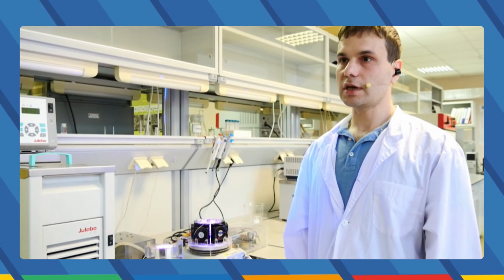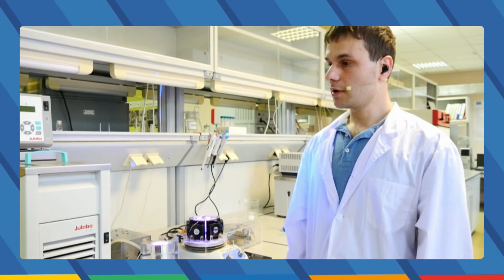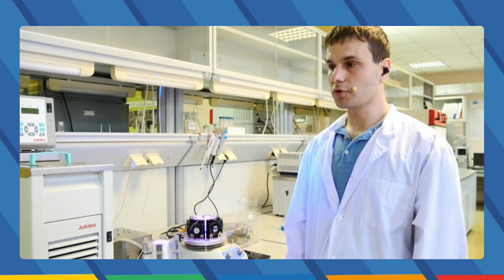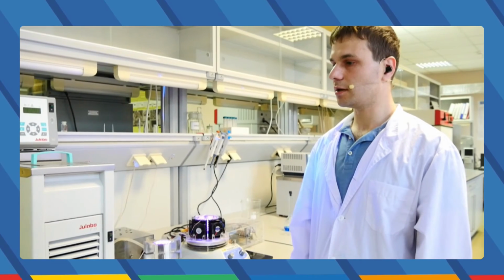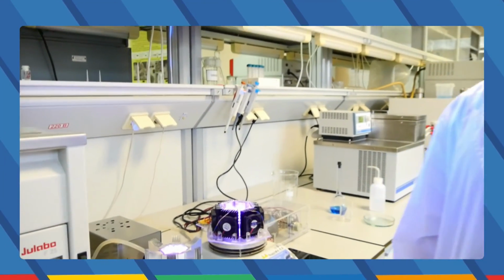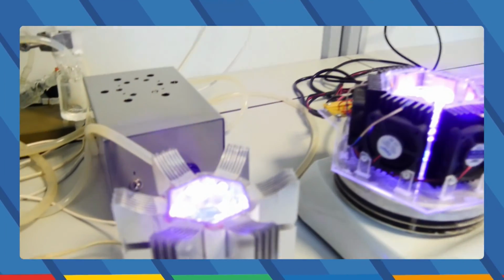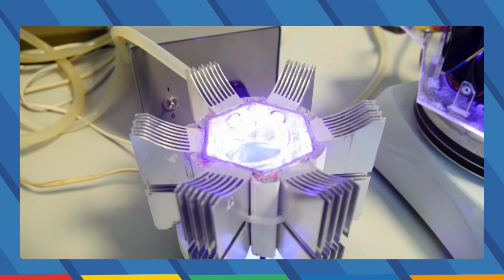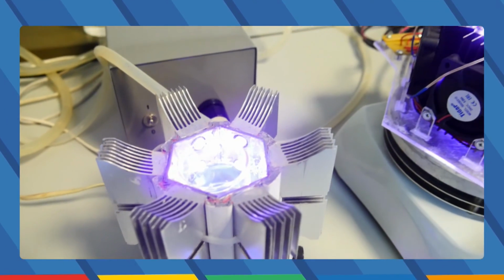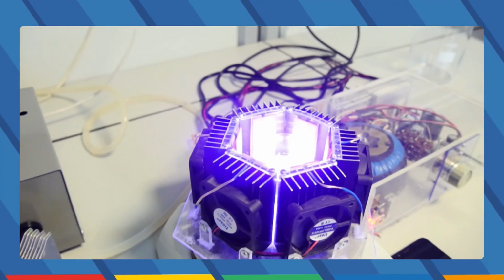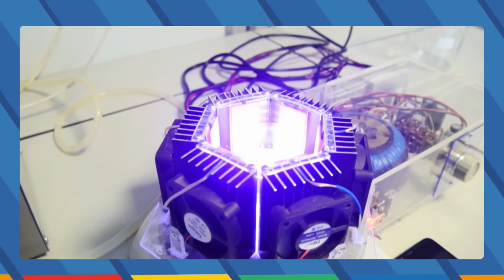So the essence of this preparation way is utilization of titanium peroxide complex as the precursor of titanium dioxide. Firstly, we prepare colloidal particles of titanium dioxide, then we dissolve them in hydrogen peroxide with formation of transparent orange or green, depending on pH value, solution of titanium peroxide complex. Then afterwards we can prepare our particles with desired size through different ways. We can precipitate our spherical particles by exchange of the solution. This phenomena occurs because this complex is not stable in organic solvents, for example methanol, propanol, and so on.